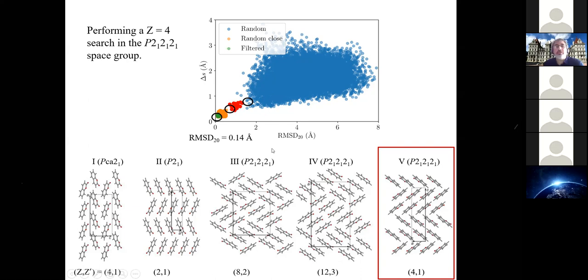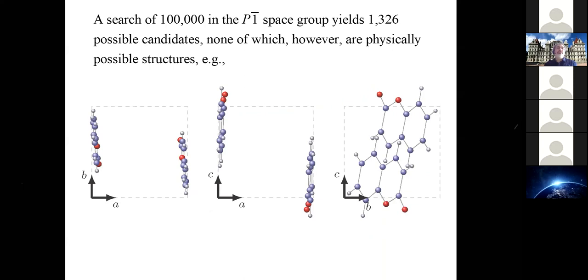Now you can ask, all right, but you kind of had this information beforehand. What happens if you pick the wrong space group, right? So let's suppose you pick one where there are no polymorphs. Well, we tried that. We actually took the P1 bar space group, and we did a search of 100,000 structures in this, and doing the algorithm yielded about 1,000 possible candidates, but none of them actually were physically sensible, in the sense that if you actually look at some of these structures, the molecules sort of get pushed up against the edge of the unit cell, and then of course you're going to have molecules basically crashing into each other from periodic boundary conditions, and so you'd have an infinite energy. So if you did evaluate the energy, it simply wouldn't be sensible.